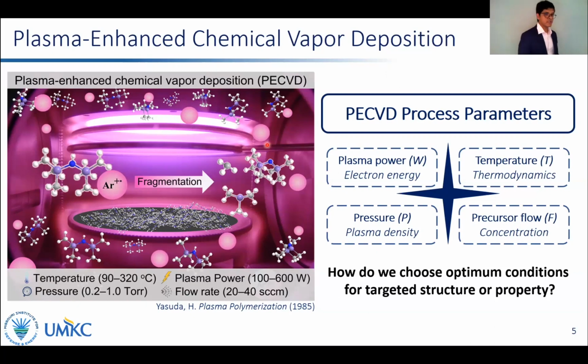PECVD is a complex process, and a cartoon representation is given on your left. A plasma is generated between 2 electrodes, and in this work, we used inert argon plasma. Chemical precursors are introduced into the plasma where they dissociate into reactive species and then recombine to form polymers and settle down on the substrate.